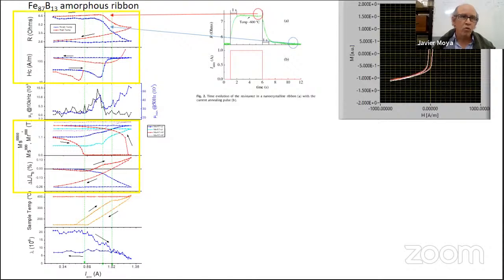Going on in the same way, we measure the coercive field. Here, the magnetization. For example, here is the Curie temperature. And here we see the elongation of the sample also at high temperature, always in red, and in blue at room temperature. In addition, here we have the initial permeability at high frequency, 10 kilohertz, and the maximum permeability at 50 hertz. Here we have the variation of the magnetostriction with the annealing temperature, and here the temperature of the sample.